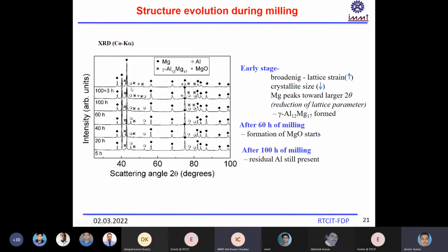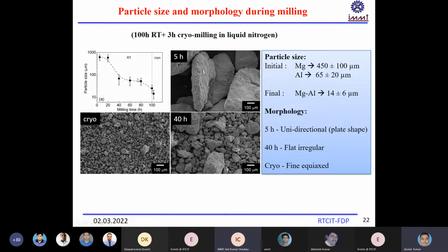But in this process, because there is a lot of handling, the handling was mostly done in the glove box, but during the processing of the extrusion or compaction, there is some contact with the atmosphere, and magnesium is highly oxidizable. Some oxidation is taking place, but these oxides are also very fine and distributed throughout the matrix. Here you can see the small gamma phase and the solid solubility, because the aluminium peaks are broadening and aluminium is going inside the magnesium.